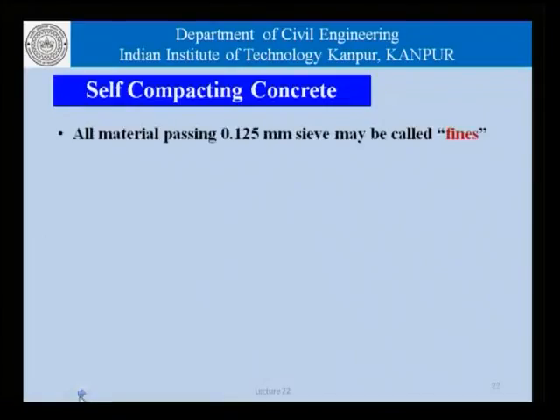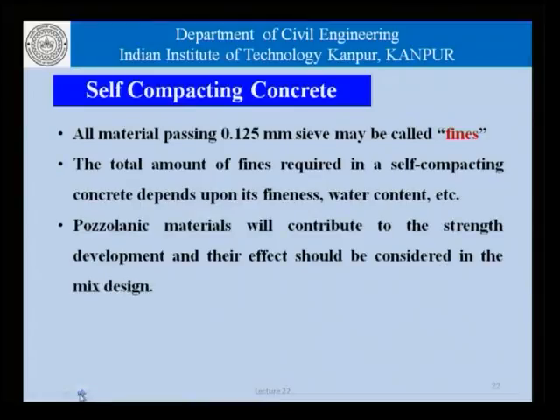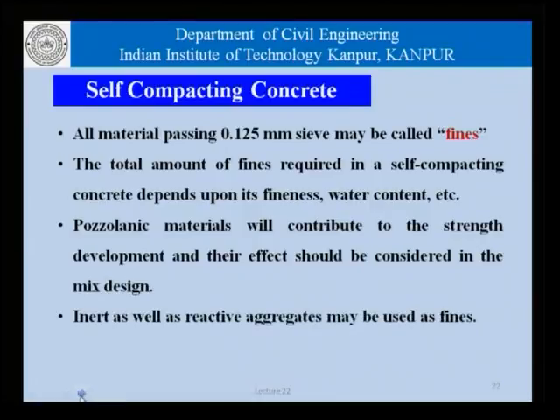Now, coming to self compacting concrete, all material passing through 0.125 mm sieve may be called fines, and that is how we were trying to define the fines in the previous slide. The total amount of fines required in a self compacting concrete depends upon its fineness, the water content, and so on. Pozzolanic materials will contribute to their strength, and their effect should also be considered in the mix design. Of course, we could use inert as well as reactive aggregate sometimes in fines, but with caution.